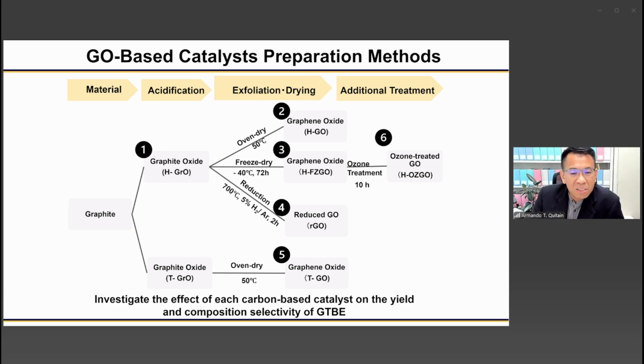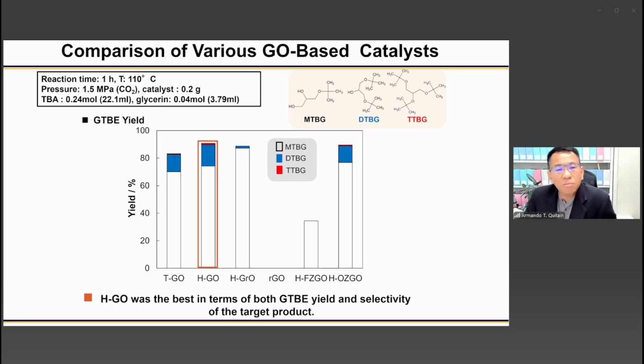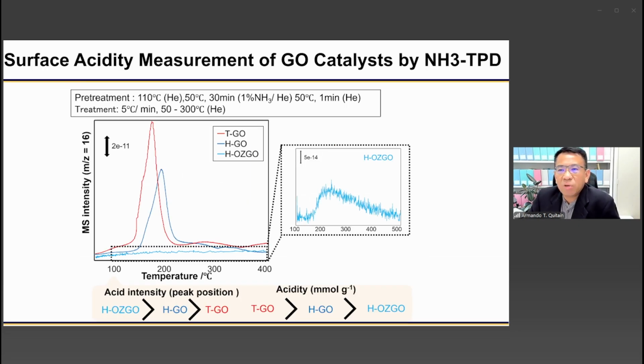And as a result, we found out that among those graphene oxide-based catalysts, we got the best results still using the graphene oxide obtained by Hummers' method. And we tried to further analyze why we are getting the best result with Hummers' graphene oxide.